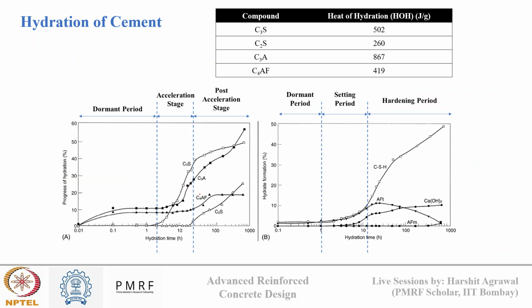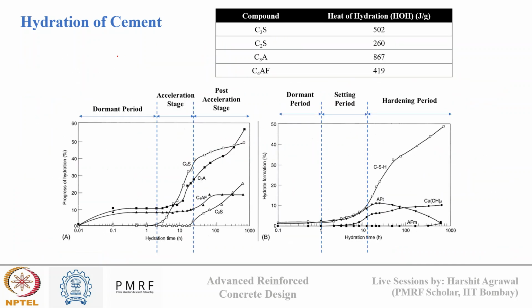Now let's talk about kinetics. This was just how cement is reacting with water, but at what rate does the reaction occur? Okay, so kinetics means the rate at which hydration is occurring. So in the first figure, we can see that in the initial few hours, C3A and C4AF start to react. Okay, and this period is known as the dormant period, the initial period.